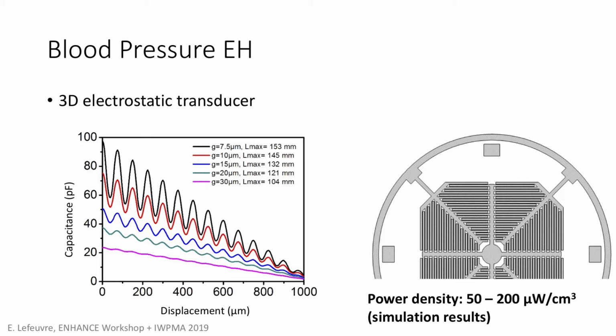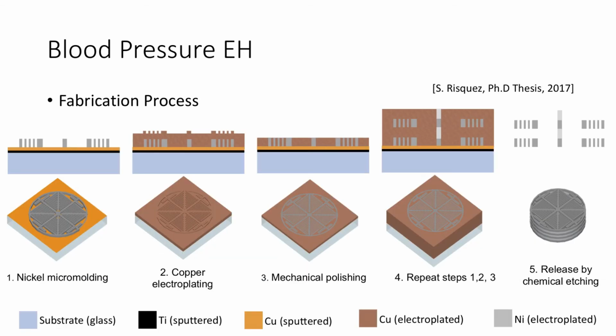And if we look at the power density, depending on the design, it's possible to harvest in the range of 50 to 200 microwatt per cubic centimeter using this design. So it's pretty okay regarding what we have in input. So now I will give you some details about the process. The fabrication process was actually one of my main motivations to do that. I was not convinced of the interest for the application, and you will understand why, but I like this process very much. It's like 3D printing. It's a layer by layer process, but you have 1 micron resolution. So you can really build 3D microsystems with a very high resolution. So I will show you how it works.